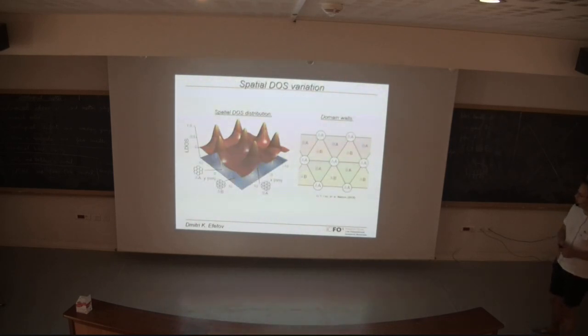Okay, and of course, if one now takes these flat bands and calculates what happens in real space, so if we just plot the density of states back into real space, what happens is that the local density of states as a function of position on the lattice is also highly anisotropic. Basically, in the AA lattice sites, you get extremely high density of states, whereas in the BA and AB lattice sites, you have strong depressions of the density of states.